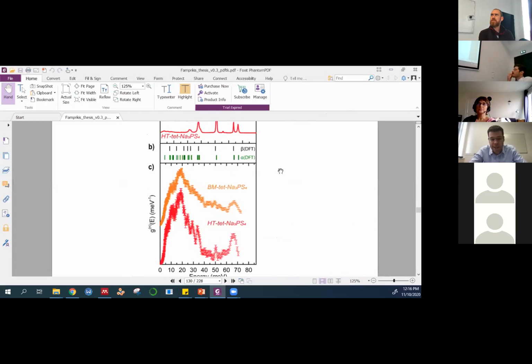In the high temperature phase, one can still say, okay, there are specific peaks at lower energy phonon modes. So the one between 60, 70, this will just be your PS4 vibrational unit. But lower, you still see sharp features for your high temperature synthesized material. You don't see that in the ball mill material, even though they're the same structure, and I can't understand how macroscopic strain changes the phonon dispersion this significantly. Do you have any idea?